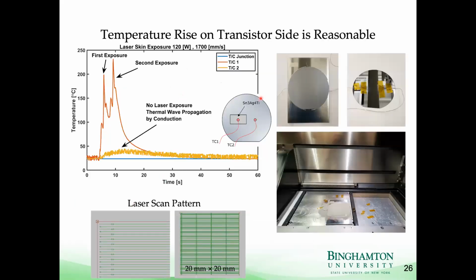We also wanted to study the reliability of the chips after printing. So we put a thermocouple underneath the silicon wafer and measure the temperature profile underneath. And we found that the temperature rise was less than 250 C on the bottom. So we think that this is quite reasonable considering other processes like soldering occur at similar temperatures.